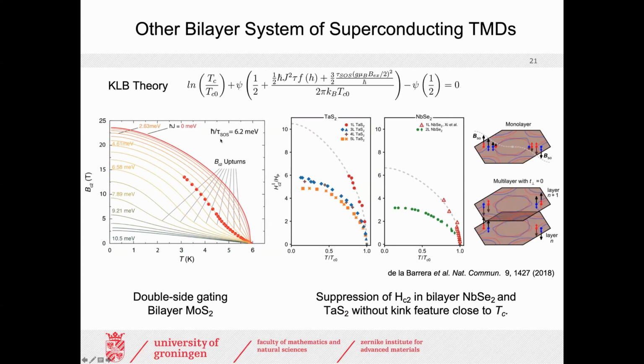And the kink actually comes from the competition between the interlayer term, energy scale of interlayer, and the spin orbit interaction. So if we increase the interlayer contribution here, we start to see that the upper critical field gets suppressed, and there start to have a kink behavior.